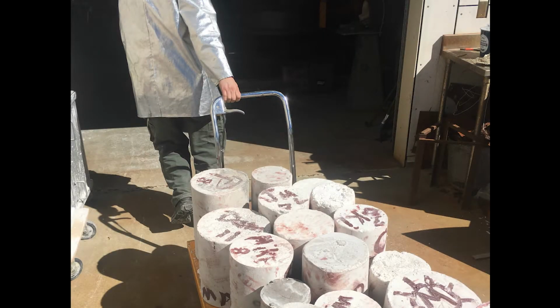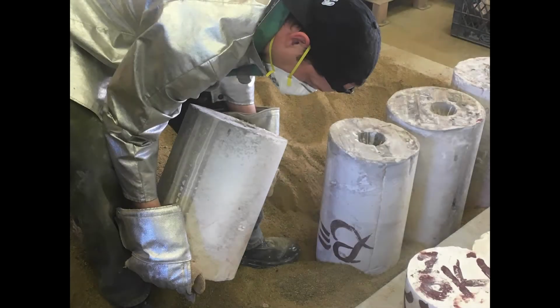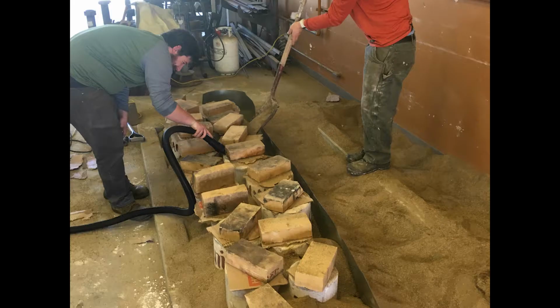On the day of the casting, the temperature will be lowered and the cylinders taken out of the kiln at around 750 degrees. They will be then taken to a sand pit and stabilized there. Evening out the various size cylinders for height will allow the casting crew to pass the crucible over without worrying about additional collision hazards. The surrounding sand will also stabilize the cylinder's temperature and help to contain molten bronze should the investment shatter during the pour.